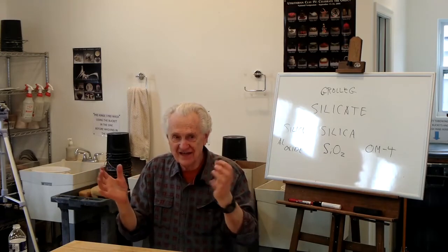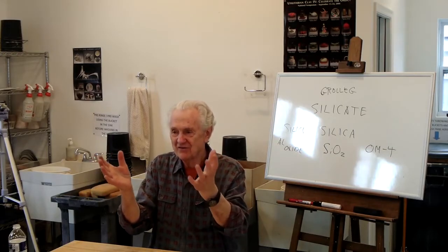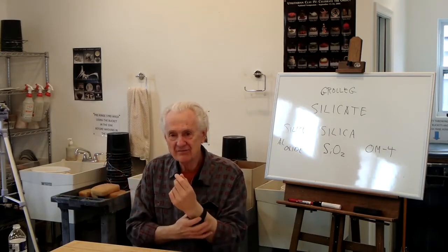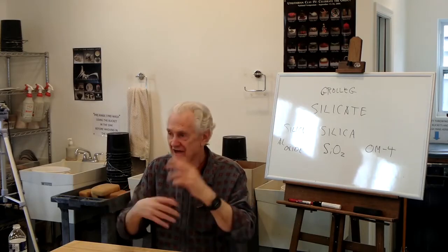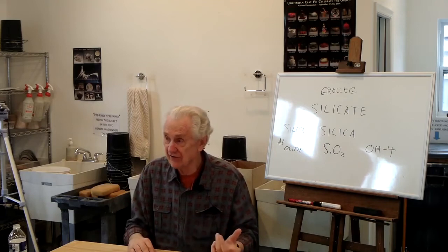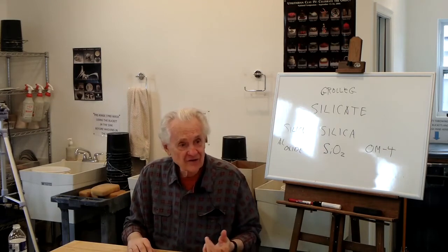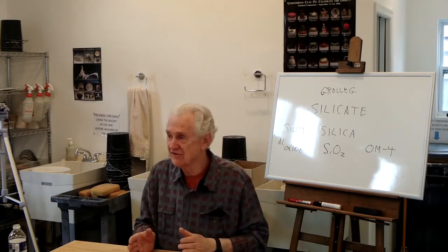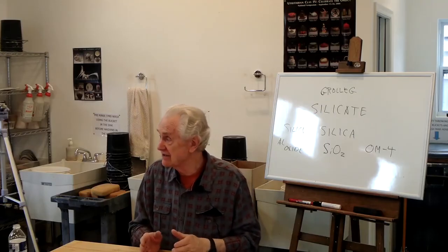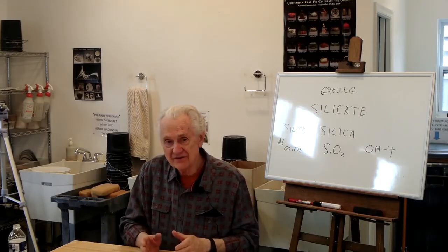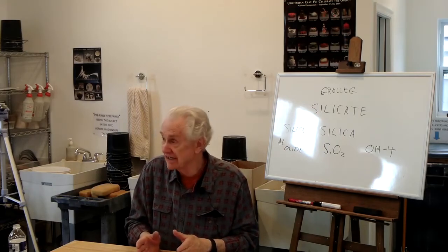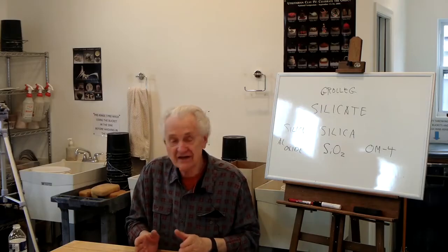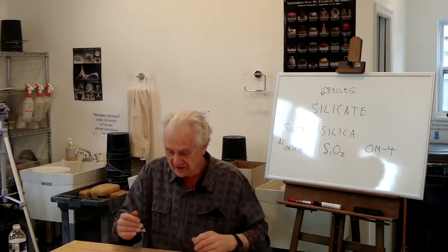So it's a great sort of sticky goop to help hold the glaze in suspension while it's in the bucket. But because it holds a lot of water, when it dries, it shrinks like crazy. And then the glaze cracks and shrinks and falls off, or it can also cause crawling of the glaze. So this is only what you call a processing additive. We don't care if it ends up in the final glaze. It does a little bit, but that's not why we're adding it. We're adding it to help us make the glaze rather than for what the glaze is going to come out like.